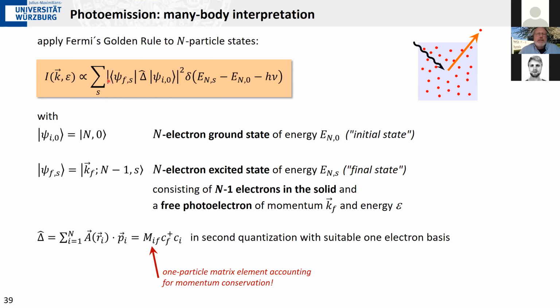This final state, again, is an n-particle state. It has one photoelectron sitting in the vacuum. That's what we find at our detector. We have a remaining system of n minus 1 electrons, which is sitting in some excited state that I label here with a generalized quantum number S. So we have an n-particle state consisting of n minus 1 electrons in the solid and a free photoelectron with momentum kf and energy epsilon. And of course, we have again momentum and energy conservation. We start out with the ground state energy, put in a photon energy, and end up with an excited state that is increased from the original ground state energy by just the photon energy package.